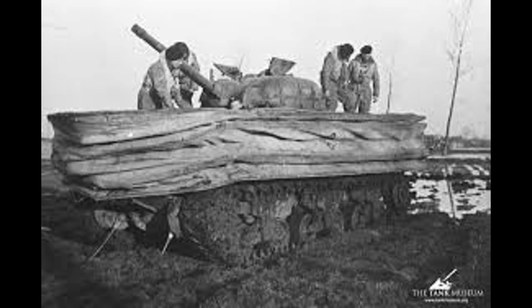The metallurgical explanation came later, after the war, when researchers finally understood what Ridley had solved intuitively. Rapid cooling from welding temperatures creates a crystalline structure called martensite. It's extremely hard but also extremely brittle, especially in cold water. The microcracks that investigators found in the Studland Bay tanks were martensitic fractures propagating along grain boundaries. Ridley's slow cooling method produced different crystalline structures called ferrite and pearlite. These were softer than martensite, but dramatically more ductile. They could flex and absorb stress instead of fracturing.